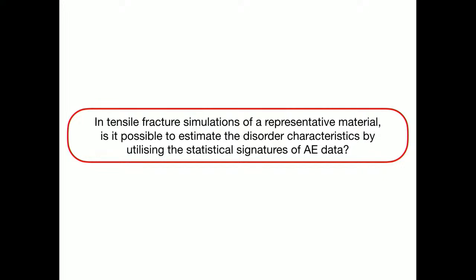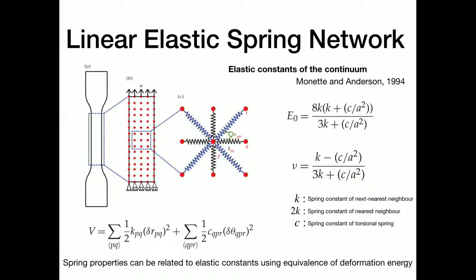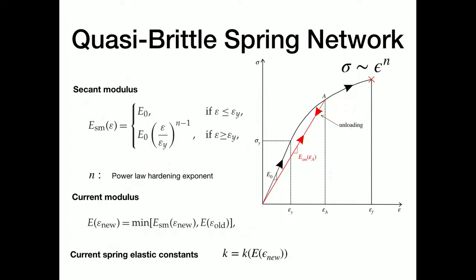In this, what we are trying to do is you have AE signal, AE data, and our model is random spring network model, in which we are putting disorder in the failure strain threshold. And can we use the information of AE data in estimation of the disorder parameter? So we use the same model, but now we introduce a little bit of nonlinearity, a power law hardening behavior. So it's linear elastic. Beyond that, it is power law hardening.